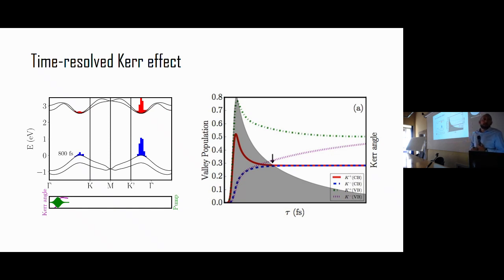It's justified somehow, yes, because the energy change that you have when you scatter from an electron state with a phonon to another electron state is smaller than the total energy, the bound energy of an electron and a hole.